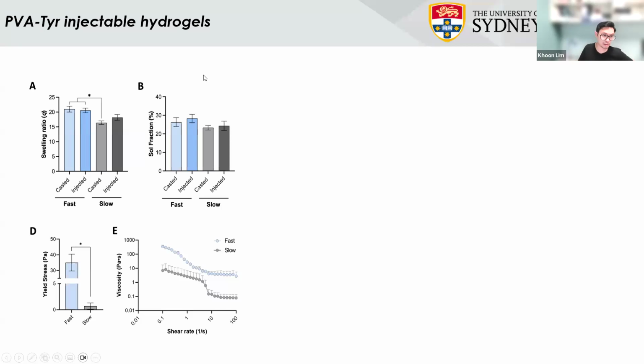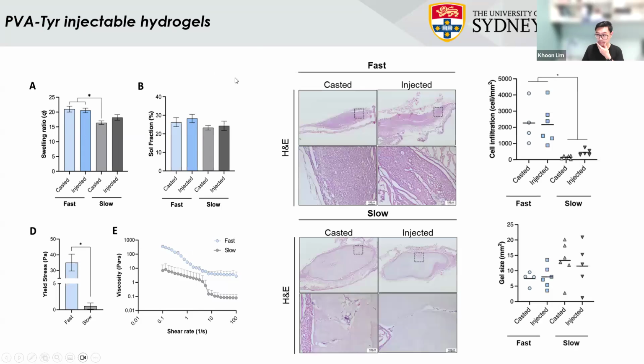These gels are also injectable, so that's actually quite cool. So what you see before was just making them into a film where you just put on and you kind of suture, right? But you can also make these gels, and they have these shear thinning properties as well, where you can put them into a syringe and you can just push them, and then they will inject out quite nicely. So we look at the difference between if you cast them as this or if you put them into a syringe and then inject them out. We don't see a lot of difference between them. We see differences more between if the hydrogel is supposed to degrade faster or slower, but that is really much determined by the amount of cross-linking density that you have within these hydrogels.